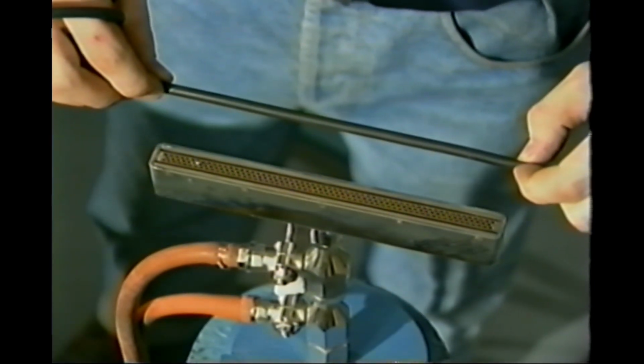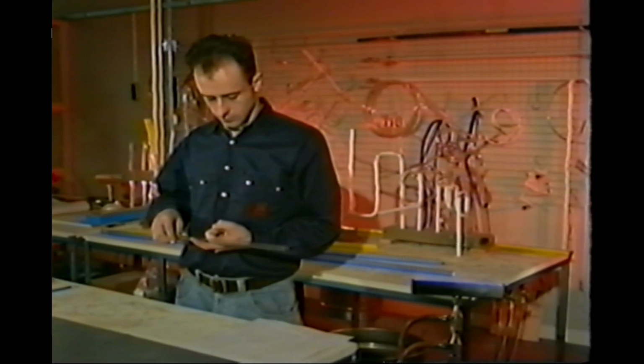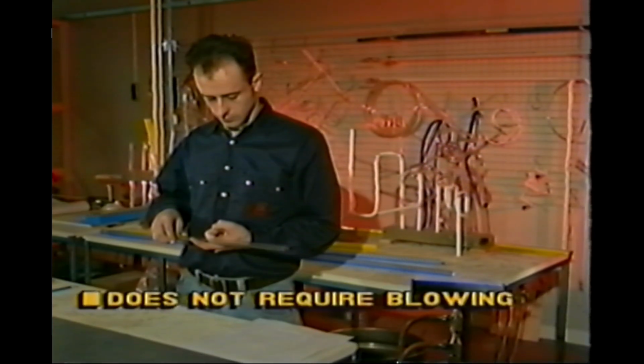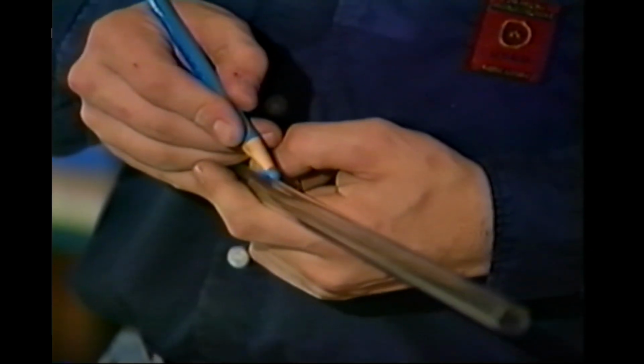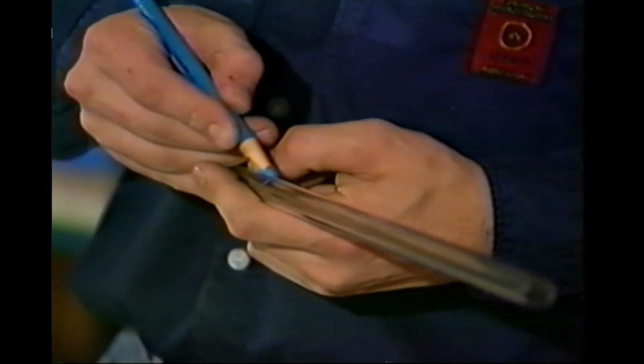Using the length you have measured, make sure the ribbon burner flame will be long enough to bend the complete half C. This particular ribbon bend is not tight enough to require blowing, because the outside radius will not collapse. Therefore, a cork will not be needed. Mark the center of the tube length with a chinograph pencil. This center mark will be used to line up with the line denoting the center of the letter C when fitted to the drawing.